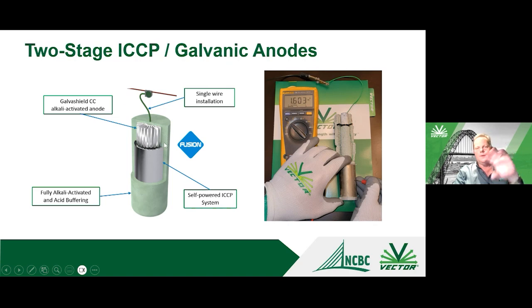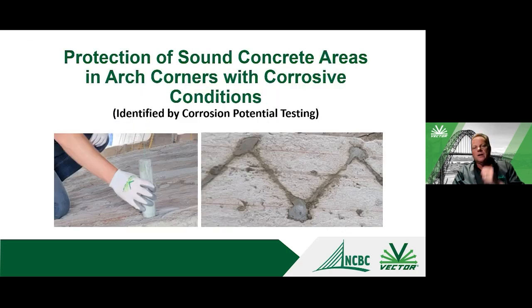over time it'll automatically switch from the battery to the galvanic anode, and at that point the galvanic anode is designed just to provide maintenance current to keep the steel from reinitiating corrosion. And these types of systems can be designed for 30 years of protection, 20 or 30 years, pretty straightforward. And so due to the amount of steel and the service life that they were requiring for this structure, like I said, they used some custom design anodes with extra zinc. And in the areas where you have active corrosion potentials, these were grouted into place, and they have an interconnecting wire that connects them all together. Then they're connected into the embedded steel.